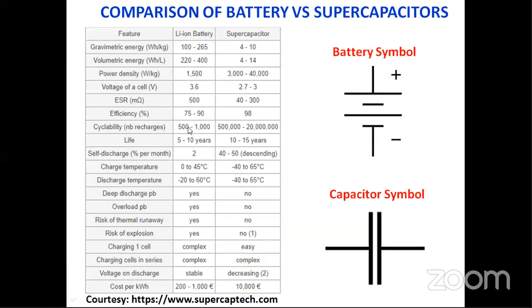Of course, the cyclability. If you're using secondary batteries in mobile phones, we have probably 300 times, 500 times charge and discharge, which means you can charge it and completely discharge it. That is one cycle of the battery's life. So you can fully charge and discharge 500 times or 1,000 times. This is why after every 1 year or 2 years, your mobile phone batteries, or wherever you use secondary batteries, have a very short lifetime. But in the case of supercapacitors, we can't define the lifetime; probably more than 1 lakh cycles have been tested so far in the literature.